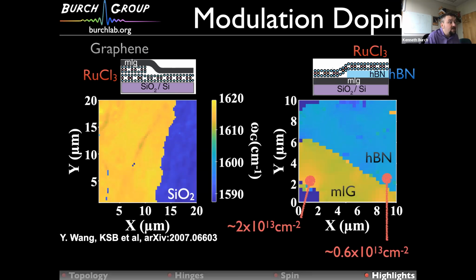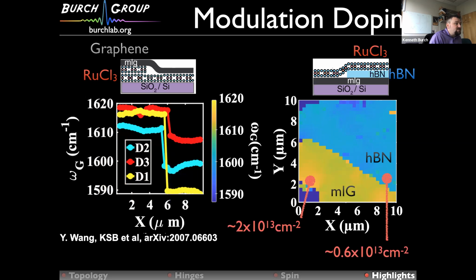And we now have, I would say, a little more evidence that you can control this charge transfer by the thickness of the HBN. And I'm not going to show it to you, but as you would expect, because the dopants are remote, you get basically the highest mobility you can possibly achieve at dopings at this level. And what's more, it's extremely short range. So if we take cuts through our Raman data, we find that this doping ends right at the border of the ruthenium chloride, roughly within 60 nanometers.